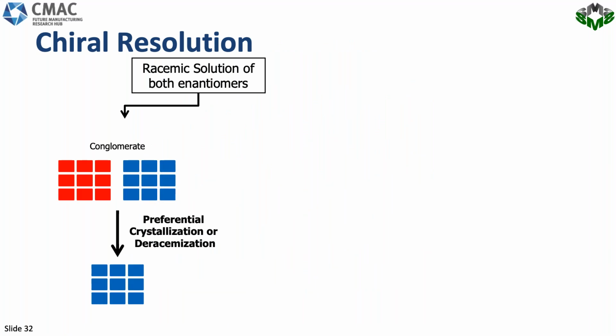So we can base chiral resolution or chiral separation on this selectivity. We start with a racemic solution of both enantiomers, let's say a 50-50 mixture in a solvent. Then we would crystallize left-handed and right-handed crystals, forming a conglomerate. And if we prevent the formation of the red crystals, we only crystallize the blue crystals, and we end up with an enantiomer product.